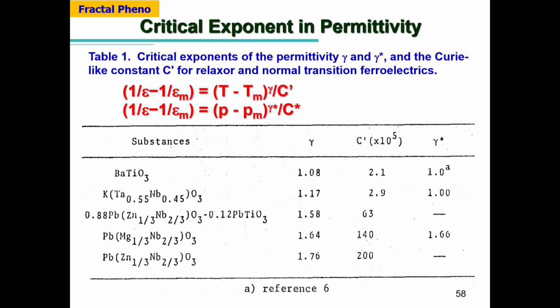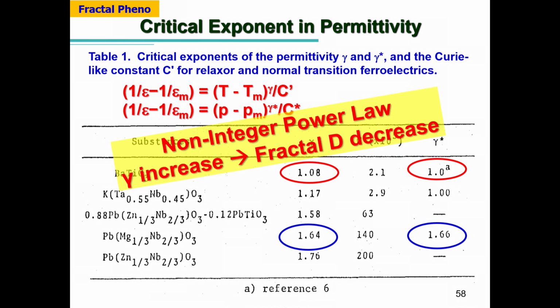So, the final table: the temperature dependence gamma and the hydrostatic pressure gamma. Barium titanate, 1.08 and 1.0, so almost the same number. And also PMN, 1.64 and 1.66, okay? You can easily understand the diffuseness or relaxation. This gamma value is a kind of parameter to evaluate the diffuseness of the transitions. So a non-integer power law provides some indication of a fractal. So a gamma increase means a fractal dimension decrease.